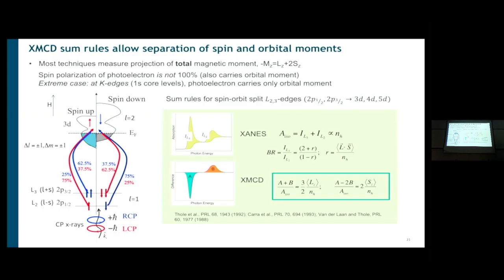So I want to spend a second here because this is important. Most magnetometry techniques measure the total magnetic moment, which is spin and orbital components. But XMCD can actually separate the spin and the orbital components of a magnetic moment. If you look at these numbers, you see that the spin polarization of the excited electrons is not 100%, it's actually 75%. The missing part is actually orbital polarization. When you excite this spin-orbit split core level, it mixes spin and orbital components, and the photoelectron carries spin polarization mostly, but also orbital polarization. So if you measure XMCD across these two edges, as shown here, the areas of A and B can be used to calculate separately the spin and the orbital components.